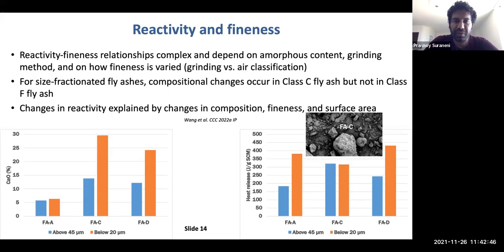One of the things that we are interested in the most is looking at processing effects and how they affect the measured reactivity. One of the things that is most complex in the way it affects reactivity is fineness. So reactivity fineness relationships depend on the material itself, the amorphous content, how you're grinding the material, if you're doing any grinding, or if you're doing air classification or sieving, which method you're using.